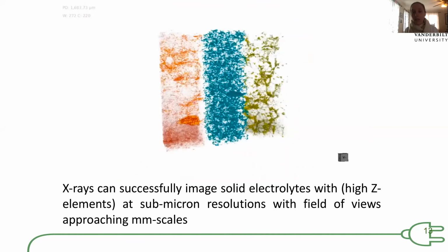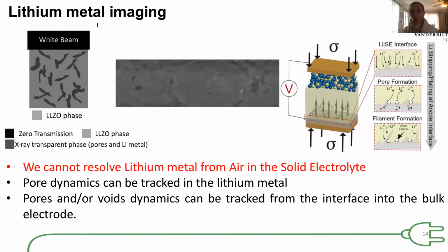At best, they're qualitative. And one thing we've been looking at recently is how we can track dynamics at lithium metal interfaces. One of the challenges with tracking lithium metal with X-rays is X-rays don't have chemical specificity naturally. Although different materials will attenuate differently, it's hard to resolve lithium metal from other low molecular weight materials, or any material that attenuates in a similar fashion.